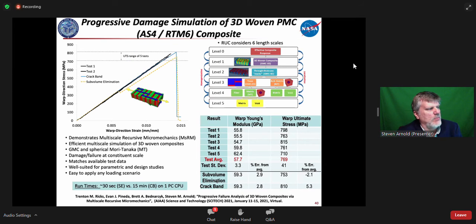Here's an example of one of the things we've done with 3D woven PMCs more recently, illustrating 5 levels of scale, where we've utilized crack band and sub-volume elimination methods to predict the progressive damage of a 3D woven. And you can see they're both quite accurate. Sub-volume is significantly faster: this was done on one CPU, but it's 30 seconds versus the crack band model, which took 15 minutes.